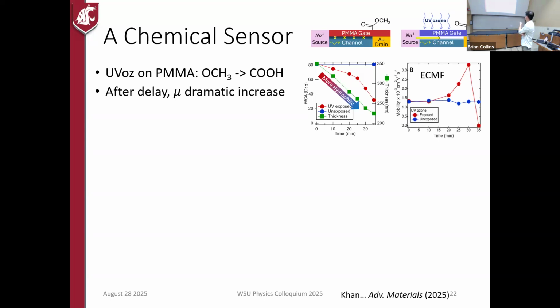And then we exposed it for different amounts of time. For about 20 minutes, nothing changes. And then after that, we get a more than doubling of the mobility, as we expected. So that's cool. But we're like, well, can we do this a little bit more real time and in situ? And can we do it electrically instead of taking videos and watching this blue thing change?